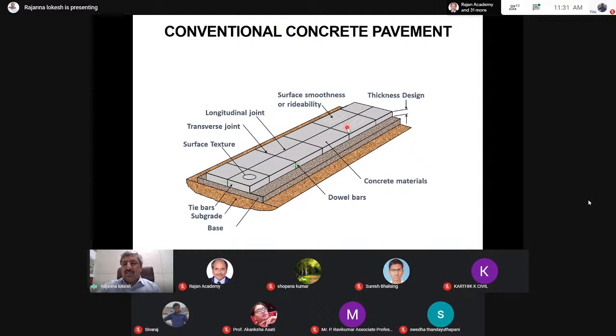The top surface of the pavement will have a texture. The texture will be either in the longitudinal direction or in the transverse direction, as shown here. On most Indian roads, you can see the texture in the transverse direction, but abroad we can see some roads with longitudinal texturing. The thickness of concrete pavement designed as per IRC 58 will vary between 150 mm or 200 mm up to 350 mm. The grade of concrete generally used for pavement concrete has a minimum grade of M30. It can go up to M50, M60, but in all possibility, M40 pavement quality concrete will always be adopted.